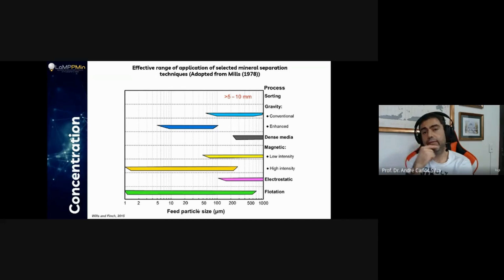Then I went to sieving. I love to sieve material, okay? If there's something that I do a lot in my lab, it's sieving. So I went to wet sieving, and I sieved about 5 kilograms of the material. I made a coarse fraction and also a small fraction. In the end, I could see the material shining at me because I could see the wet material completely clean. We could see a lot of sulfides, and they are very, very beautiful sulfides. And just by looking, we can say that it's arsenopyrite, pyrite, and even some small amount of chalcopyrite.